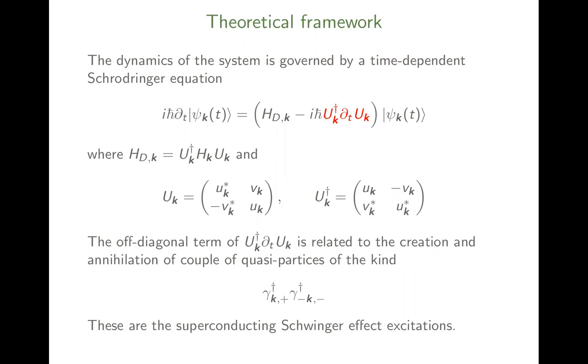So it might be that if you get a strong enough electric field, you have some effect due to the fact that the electric field is penetrating in the superconductive phase, about the order of the penetration length, of the coherence length of the superconductivity. So my point was that it could be that you are destroying superconductivity because you are forcing a too strong electric field, even before you consider the third direction. It's impossible to sustain the superconductivity.